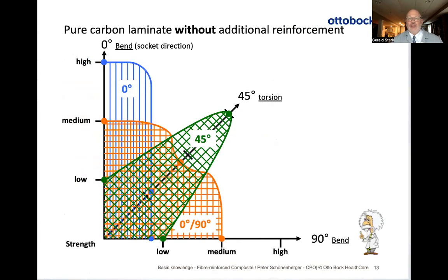Here's the thing, if you get that weave wrong and how you lay it up, you decrease the strength by quite a bit. So when you look at this weave, you have to look at how much torsion you think you're going to get, how much bending, and how much you're getting in the 90-degree bend. So that's why we typically use 45-degree twill or 45-degree weave when we're talking about prosthetic wet lamination.